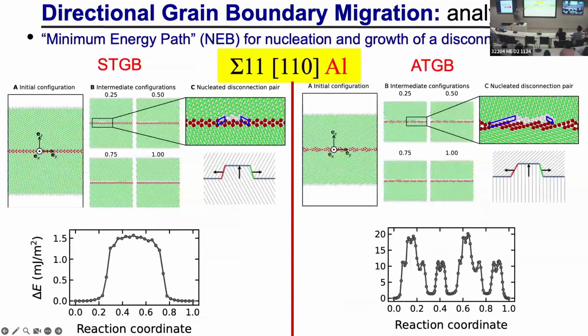Okay, so this is a sigma 11 <110> tilt boundary in aluminum. This is a symmetric boundary. There are some details about the nudged elastic band calculation, but we don't focus on that. But if I look at the energy to form this double kink and propagate it out, I have a barrier that looks like this.